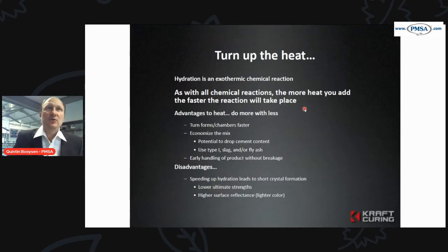What is required? During the hydration of cement, from 2 hours onwards up to 48, well, the hydration continues for quite a long time, but especially in the early stages, there's a chemical reaction giving off exothermic heat. The chemical reaction has a byproduct, which is the exothermic heat. That heat is free heat. You've already paid for it in every bag of cement.